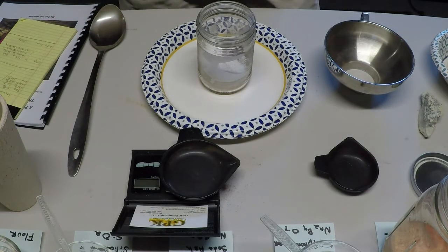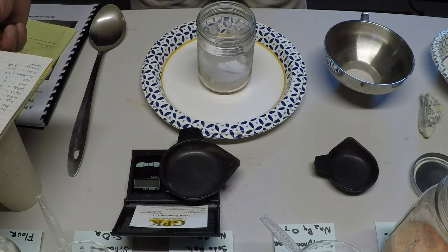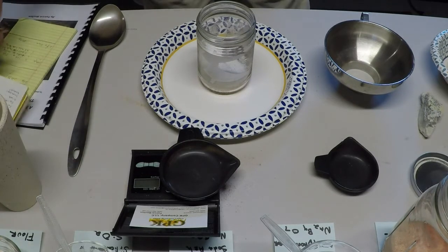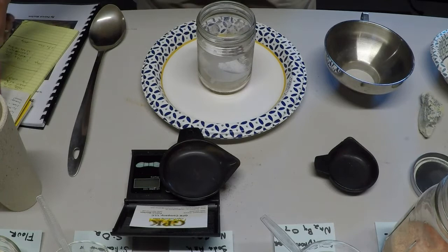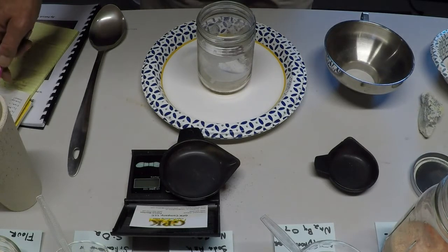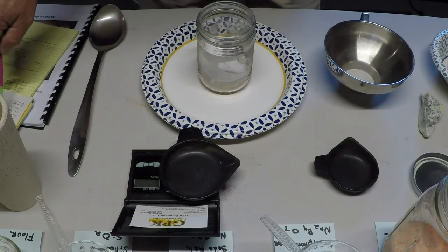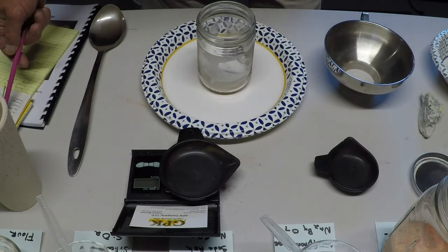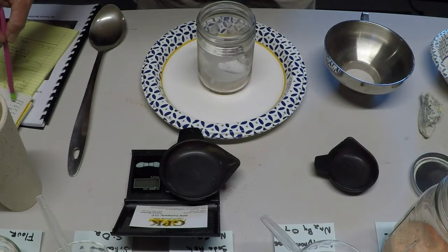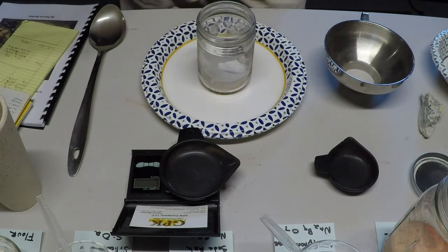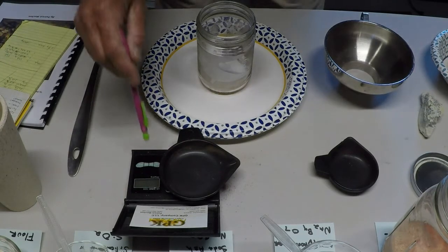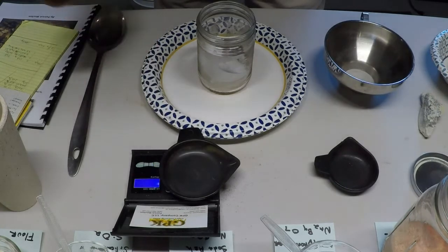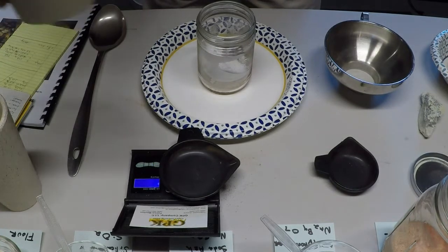Trying to control that lead prill is really, really difficult. And if you have any extenuating circumstances, say you got a little bit of pyrite, a little bit of arsenopyrite left, or a little charcoal left, it'll reduce more of the lead oxide than the carbon source that we're going to put in. But we can stand that because we got a great big cupel here.